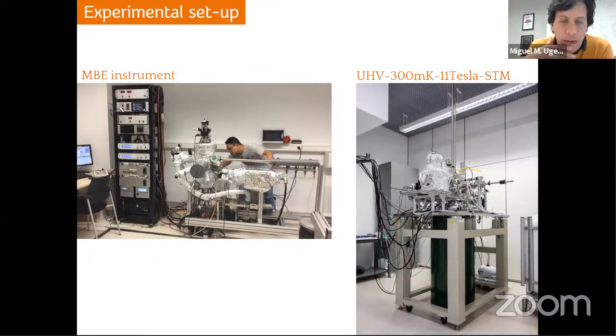This is the experimental setup where we have carried out most of our experiments. This is the UHV MBE instrument working in ultra-high vacuum conditions. Here you see when growing one of the samples. So after the growth, basically what we do is cap the 2D material with an amorphous selenium capping layer that allows us to transfer the sample to any other UHV system for further characterization, for XPS, ARPES, etc.